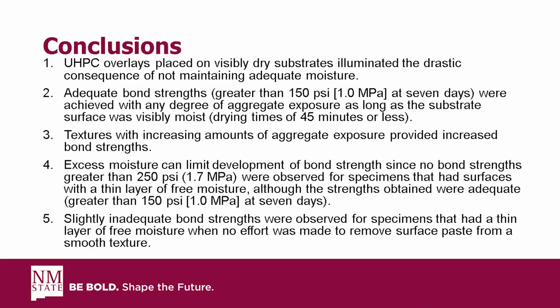Okay, so conclusions from the study. UHPC overlays placed on visibly dry substrates had drastic consequences for maintaining adequate moisture. So that was shown here, where by drying it more than those 45 minutes of dry time, we're not developing any bond. And then adequate bond strengths greater than 150 psi at 7 days were achieved at any degree of aggregate exposure when we had essentially a moist substrate surface. Bond strengths increased with increasing amounts of aggregate exposure, and that was just from this one here. As we expose more aggregate, we get more bond strength.